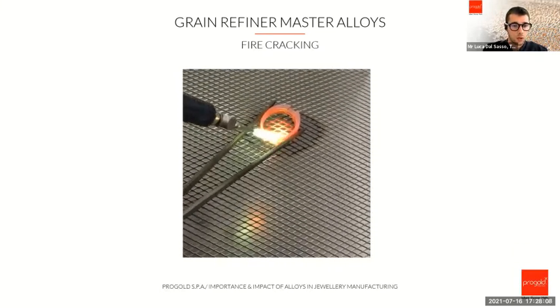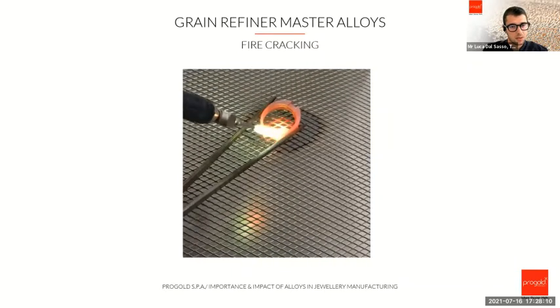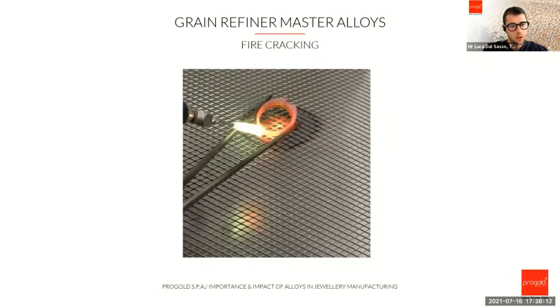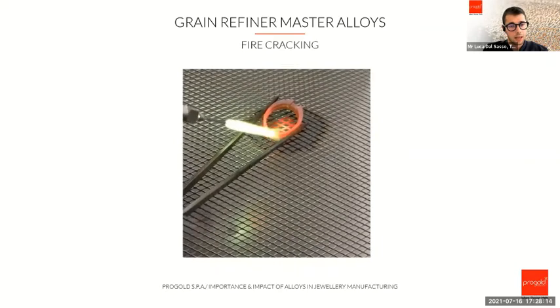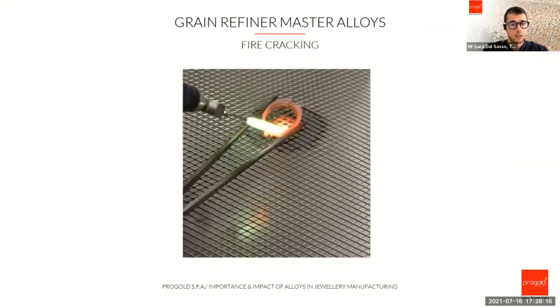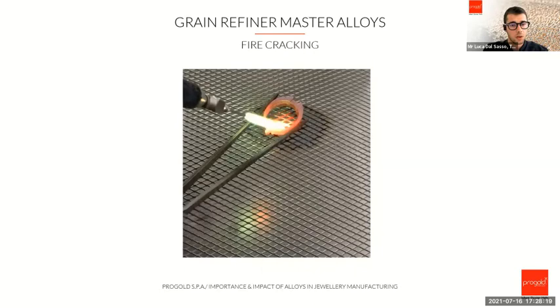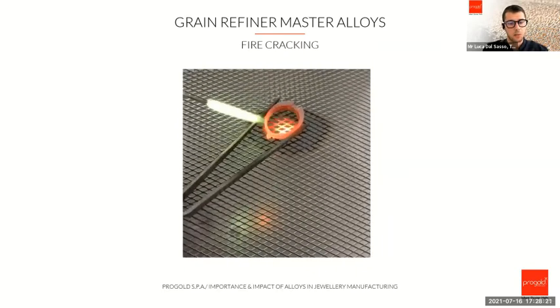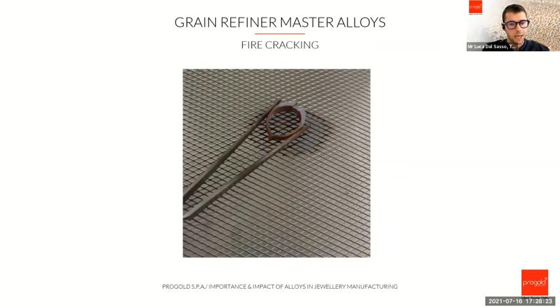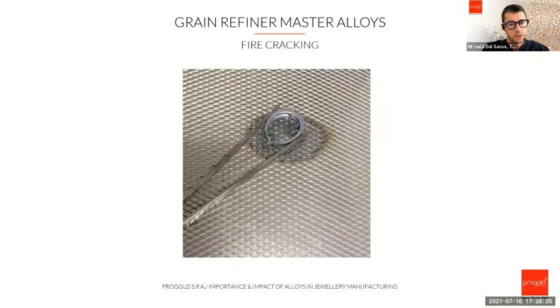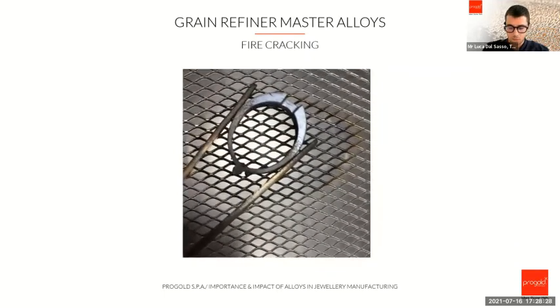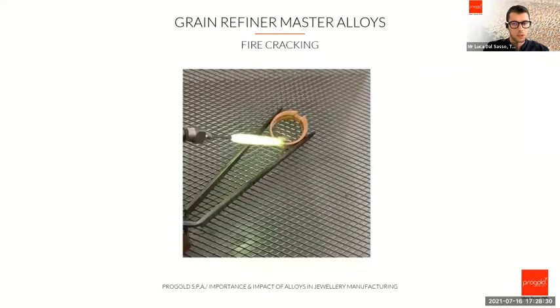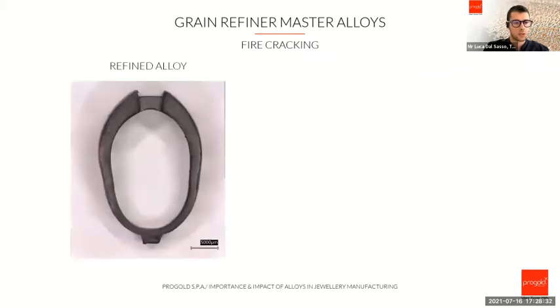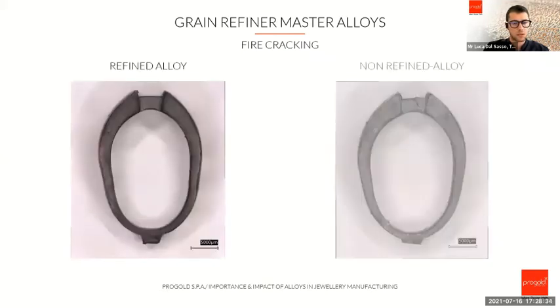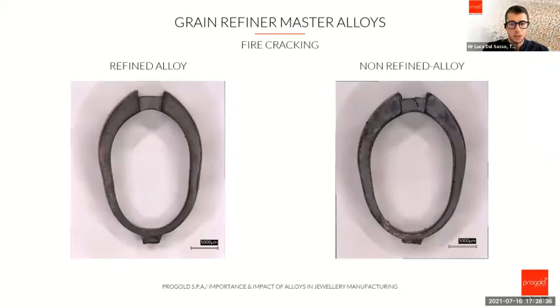So going on with this procedure, you can see that the ring starts deforming. And if there's a grain refining master alloy in this piece, we will see that the object starts becoming all black, but on the upper side, it will not break. The other example is here: refined master alloy, non-refined master alloy. On the right one, we can see that the crack is huge.